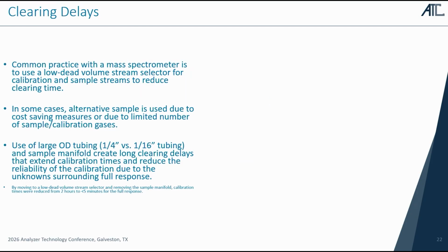Additionally, there were long clearing delays, reporting sometimes 2 to 3 hours, if not days, to get up to a T95 with the actual field installation of this system. It is common practice with mass spectrometers and any ambient air type system to use a low dead volume stream selector for calibration and sample streams to reduce clearing time. In some cases, alternative sampling is used as a cost savings measure for the total overall project, or due to the limited number of sample and calibration points.